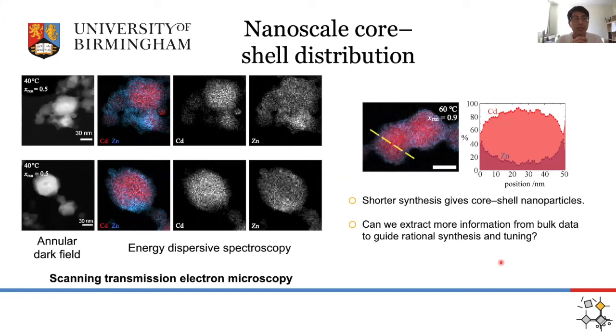My student Kieran Orr did a systematic study conducting 99 different reactions over 24 hours as a function of the cadmium fraction in the reaction mixture and temperature. At Diamond beamline I-11, we collected high-resolution synchrotron X-ray diffraction patterns. The peak shape is surprisingly asymmetric, suggesting quite condition-dependent heterogeneity. A standard analysis of X-ray diffraction is insufficient to resolve these spatial distributions — so we turned to Sean Collins, an expert in scanning transmission electron microscopy, whose images showed that these particles have a cadmium-rich core surrounded by a zinc-rich shell — core-shell nanoparticles.